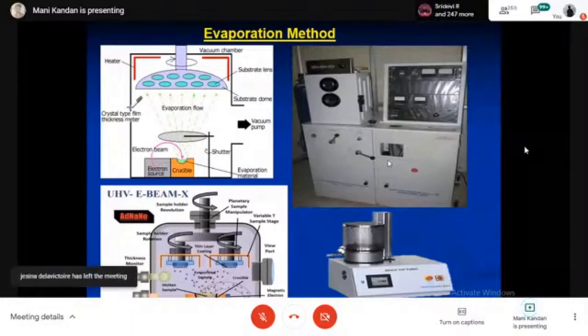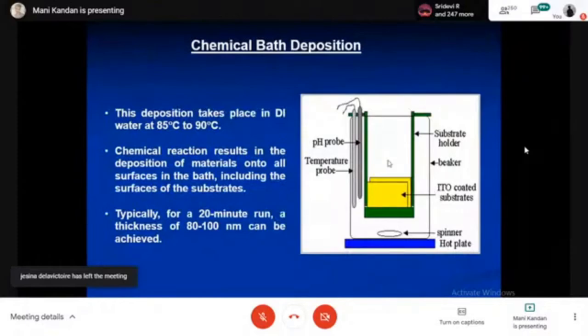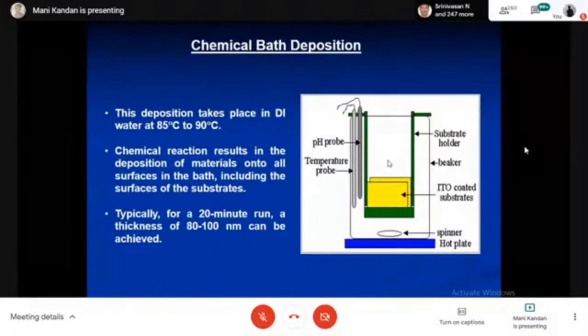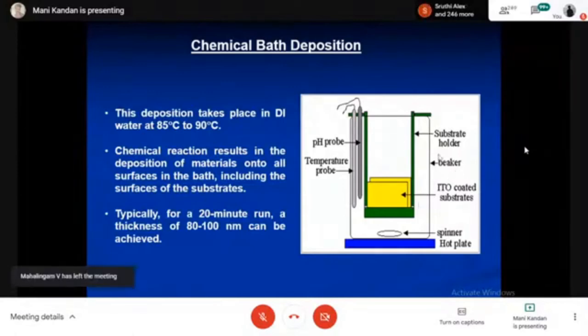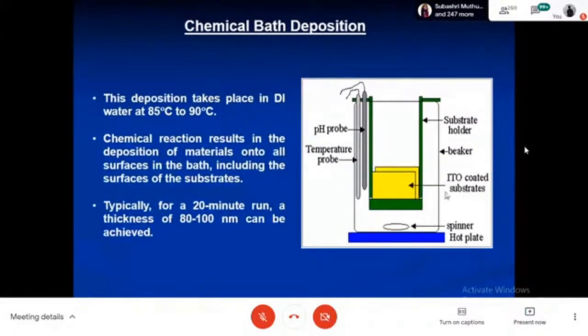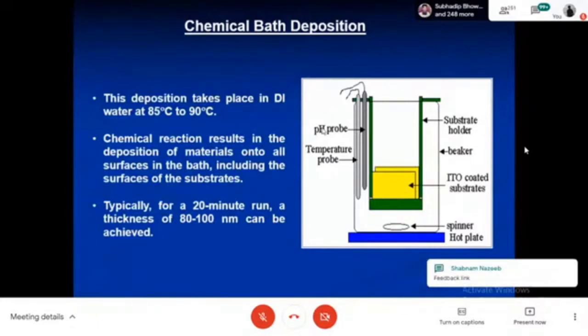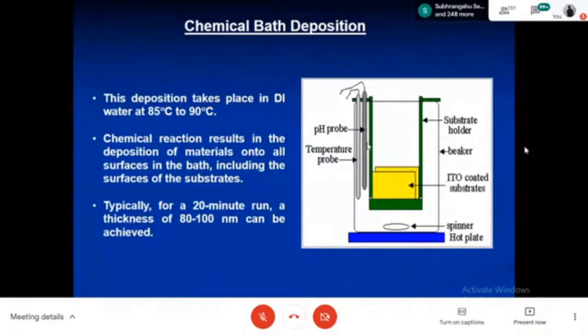Okay, so there are still some simple techniques where we can make the 2D layers, which is chemical bath deposition, where you take the material in a glass beaker or chamber, and then introduce a sample holder, and this is the ITO coated glass substrate which is introduced there. Then you have the hot plate to maintain the homogeneity of the solution. To control the pH, you have the pH probe, and to control the temperature, you have the temperature probe. Everything can be covered with an evaporation-controlled seal, and then you induce the deposition on the substrate. The typical temperature is around 85 to 90 degrees Celsius.